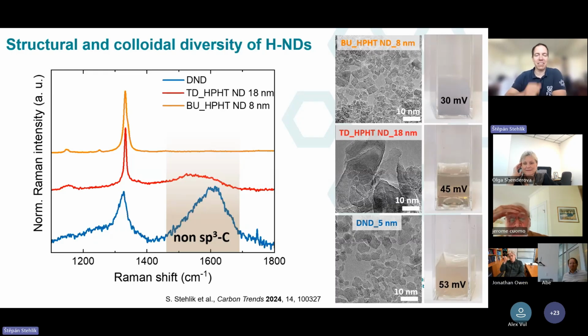Yeah. So that's a perfect point. Of course, we thought about that, and so far we don't have any good data about that. I totally agree that especially this top-down HPHT nanodiamond is actually very unique, that it has simultaneously the positive zeta potential, which is unlike the bulk hydrogenated diamond, but at the same time it has this transfer doping like conductivity and the negative electron affinity. So at the moment, we don't have any other characterization, like the Hall measurement, whether we have the holes as carriers or even electrons. This we don't know yet.